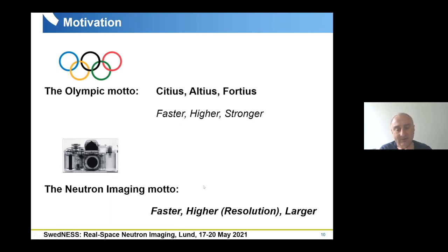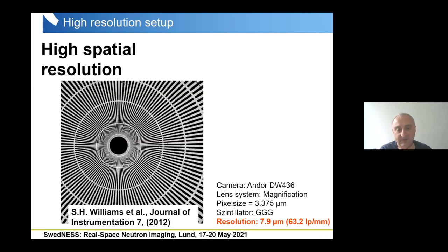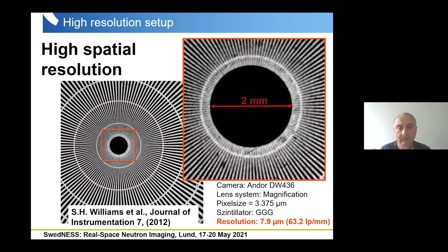And today I'll focus on all these aspects, starting with the high resolution applications. So this is one result which we achieved quite a while ago, about 9 years ago, where we were able to perform imaging with a resolution of about 8 micrometers. And this is quite a good achievement for neutrons, and you see why we are very proud of this. So finally, you can see here that we can resolve the resolution pattern in quite a good way. Here, the distance between the stripes is about, I think, 10 micrometers. So the resolution of 8 micrometers was quite a good achievement.